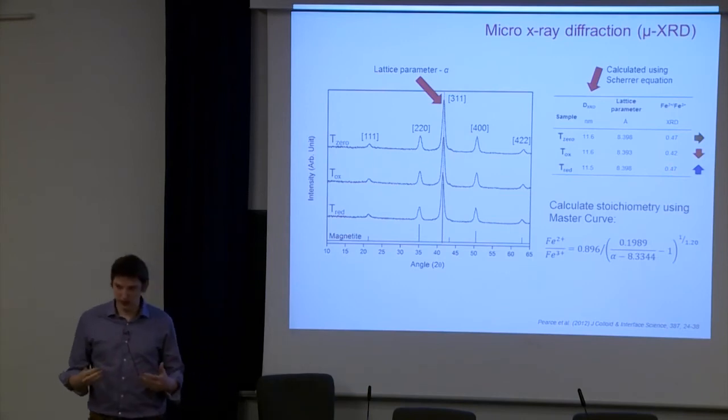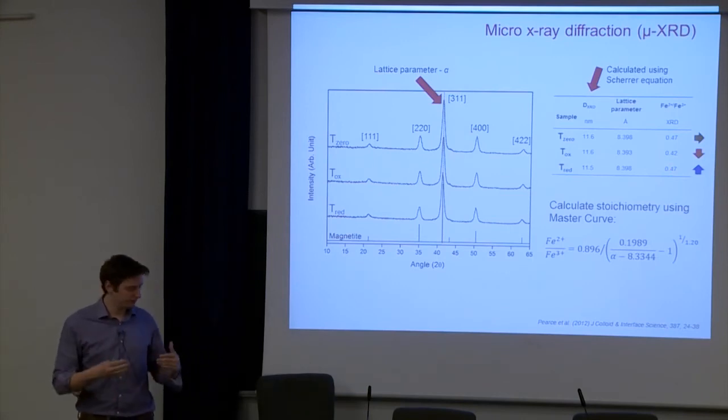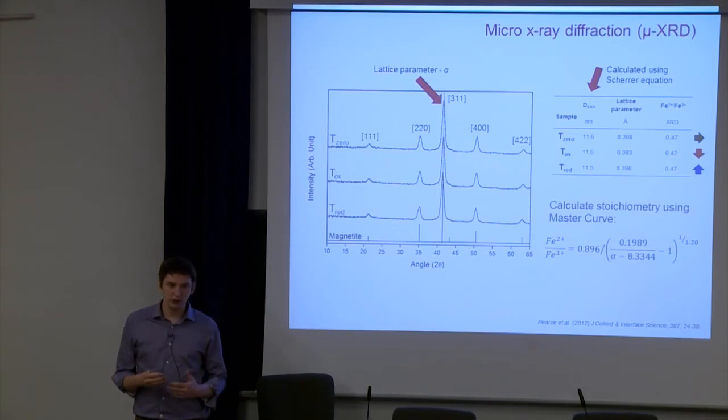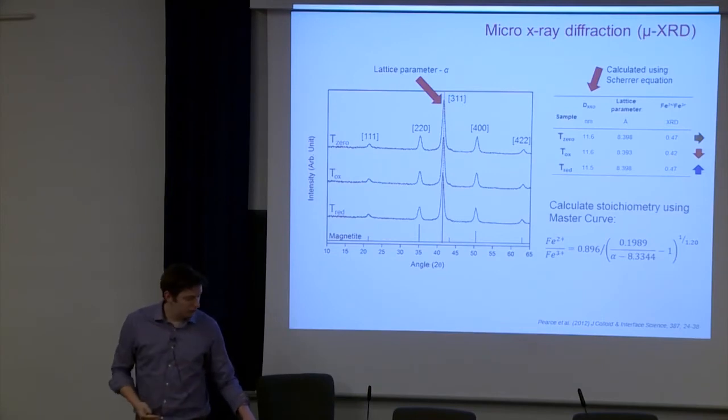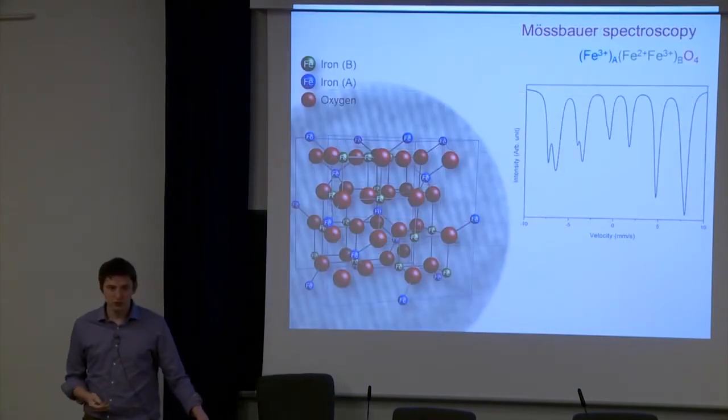So it's kind of indicating along the lines of what we're thinking, that the oxidizing bacteria are oxidizing magnetite, and then the reducers are reducing it. So for more evidence, we've also turned to Mössbauer spectroscopy.